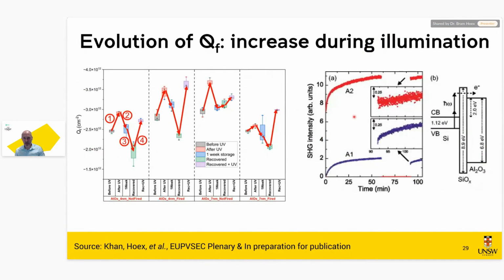And this is like the evidence where we also showed that we can increase. So in this case, with second harmonic generation, we can see this charge injection. Here we switched off the laser beam for a while, and we can see the direct evidence that part of the charge was leaked back into the silicon. So this is very consistent with the understanding that we have had for the system for almost 2 decades.